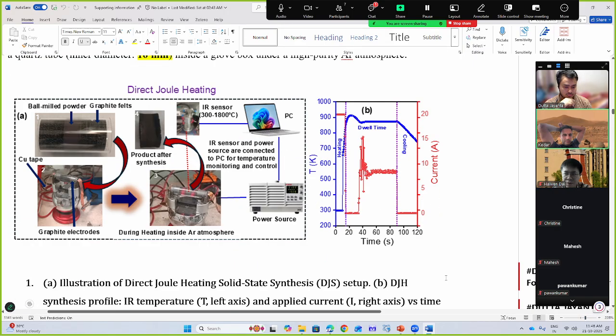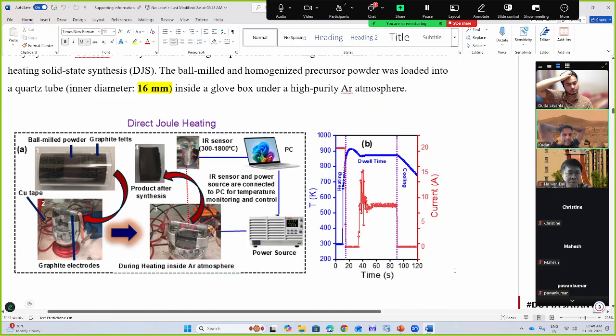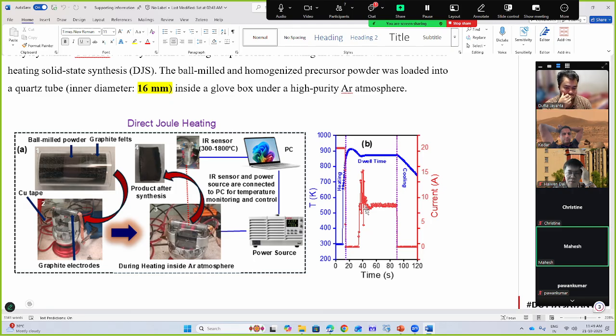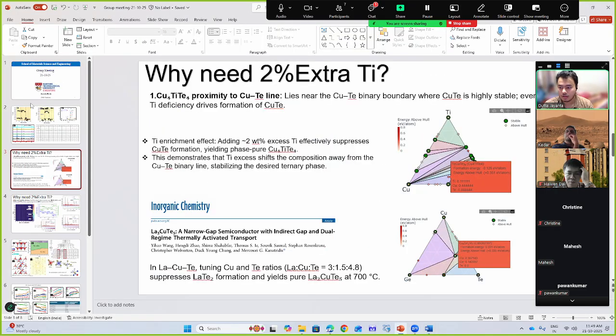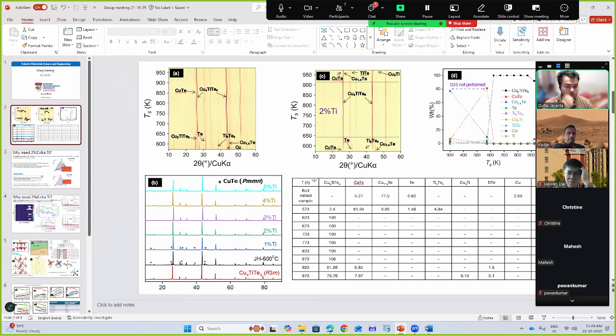So you see around 700 K, there's a change. It goes up very fast to 700, right? Yes, this cannot record the temperature below 300 degrees, the IR sensor can record after that. I see. Is the initial step ball milling? Is it stoichiometric elements, or is any compound already formed? Did you check? So this is actually with 2% titanium addition.